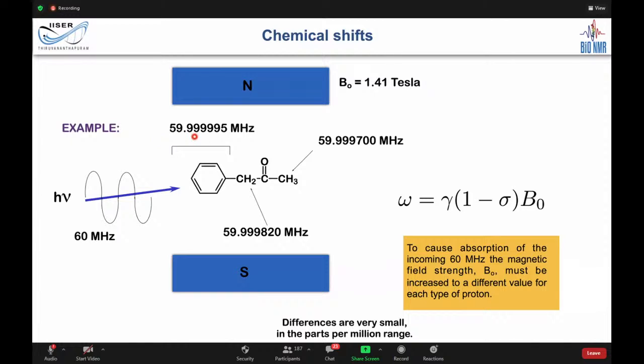This is quite a high frequency because that is quite de-shielded, right? It's like the electrons are no more there. While here the methyls are well shielded. It is a little far away from 60 megahertz, at 59.999700 megahertz. Though if you look at the absolute numbers, it looks very small, you remember this is megahertz. If you put it in hertz, it's still a significant amount, right? So you see that the differences are really small, and those differences are what the chemical shifts are.